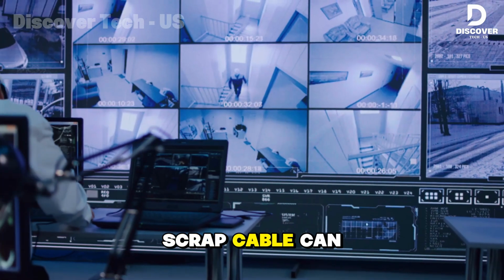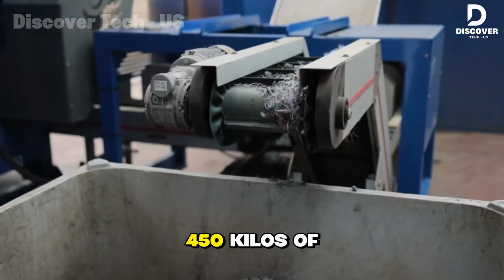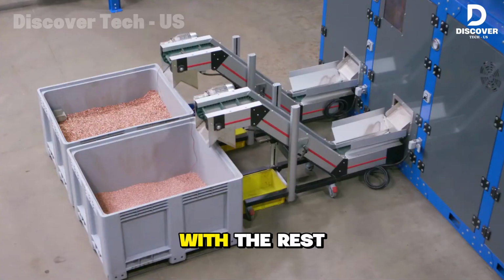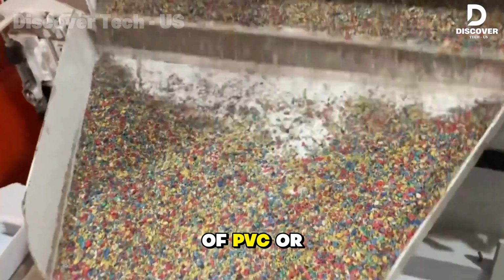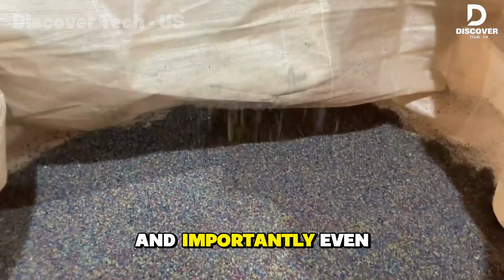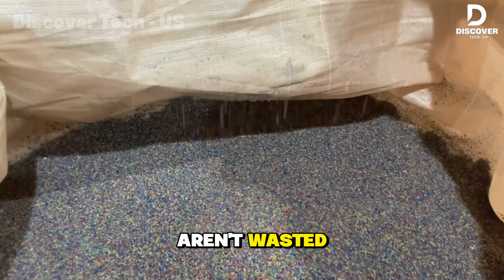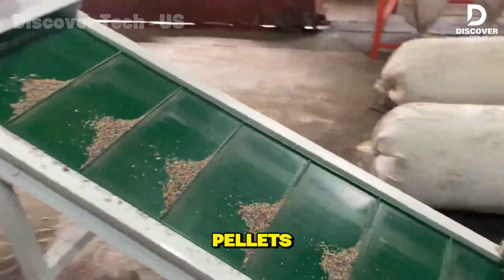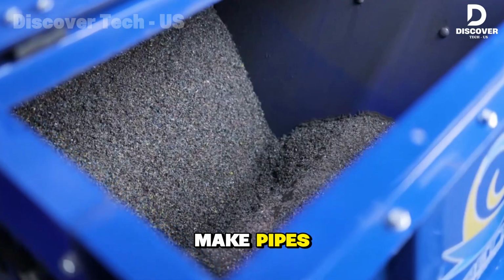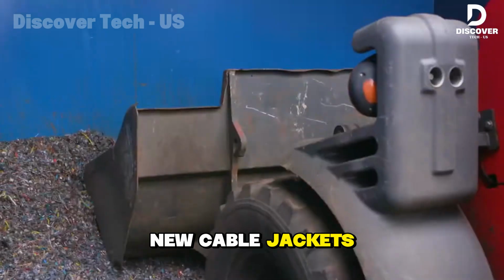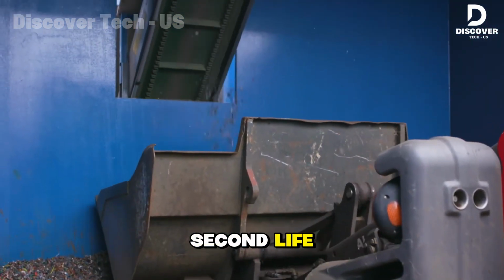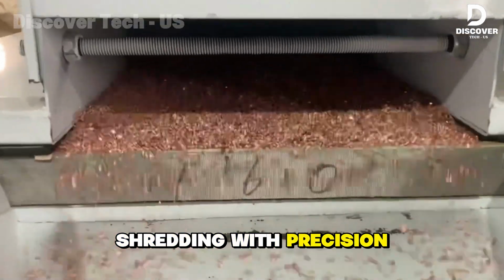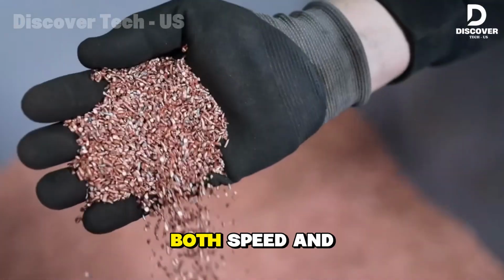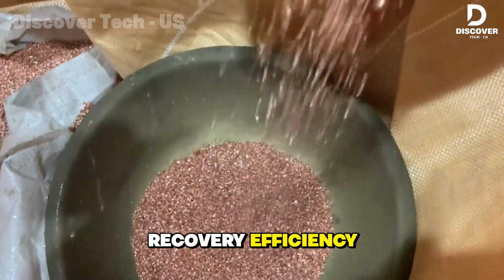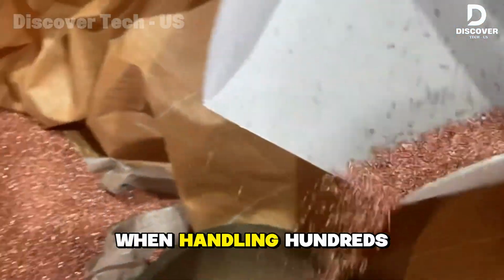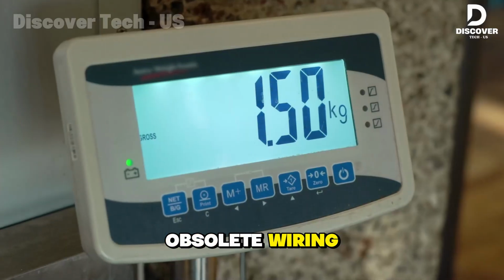Each ton of scrap cable can yield 400 to 450 kilos of pure copper, with the rest made up mostly of PVC or polyethylene. And importantly, even the separated plastics aren't wasted. Once cleaned and ground into fine pellets, they're reused to make pipes, liners, or even new cable jackets, giving them a second life. By combining bulk shredding with precision sorting, scrap yards boost both speed and recovery efficiency, a crucial advantage when handling hundreds of tons of obsolete wiring every year.